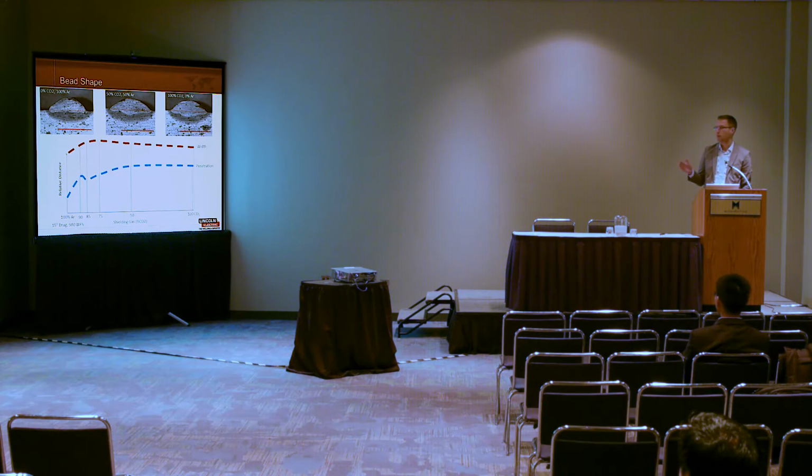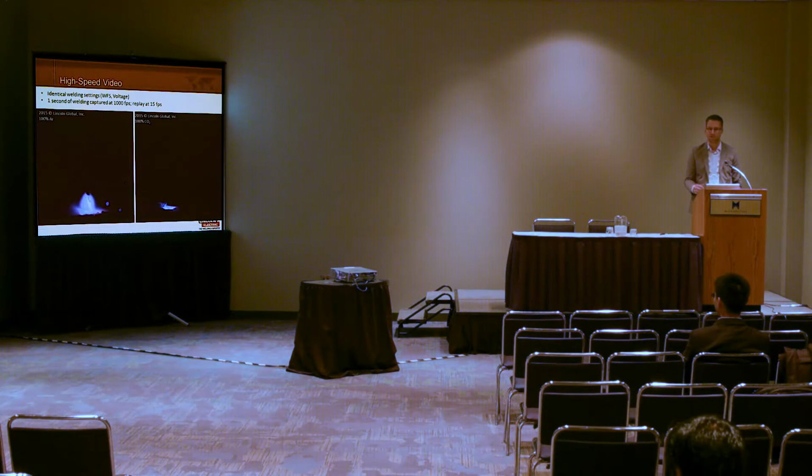And as you move to the higher amounts of argon, you see a slight decrease in the amount of bead width at the very high amounts. But really the bigger effect is that penetration drops off steeply as you get past 75-25. And so to investigate why this effect is and show it more graphically, we did some high-speed videos. I wasn't sure if these would show up well enough, but it looks like they're okay.